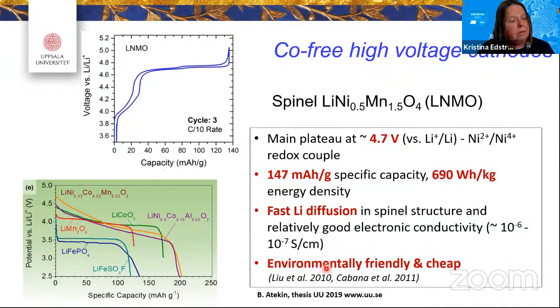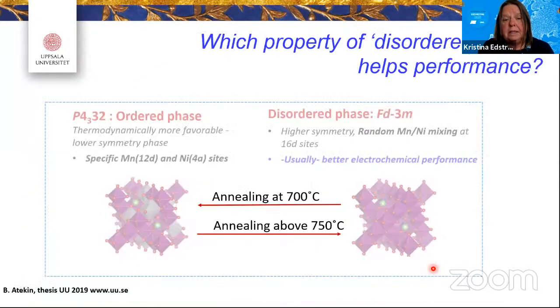And just to say something about the Tesla ideas, we now go for nickel manganese oxide, and they will even increase the nickel more than in this example. What is happening then is that you get to much higher voltage where you have this lithium insertion and extraction in these materials, compared to different NMCs and more classical materials. And this influences the volumetric capacity. But if you go to these high potential plateaus, you have other problems arising. What is also good with this material is that it has fast lithium diffusion and is quite environmentally friendly and cheap. But the stability is a question.